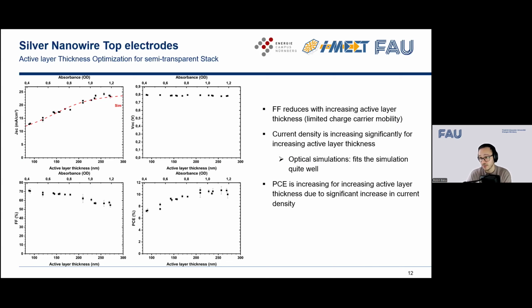However, we're talking about upscalable processes and materials. So we have to transfer or get rid of our evaporated silver electrode. And with nanowires, the trends are completely different. Nanowires are the preferred top electrode of choice in this case because they're easy to coat, they work well with blade coating, and they even allow for semi-transparency. But due to the semi-transparency, we also lose the back reflection, or a significant amount of it.